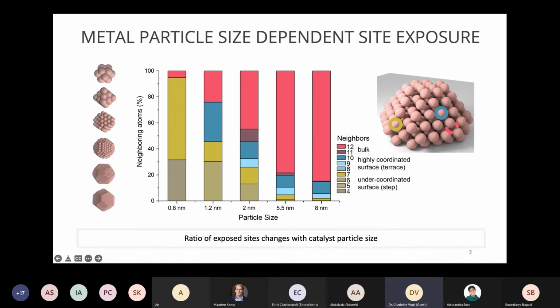And of course, in supported metal catalysts, we want to make as much use out of the often most expensive part of a catalyst that we have, which is the metal. So we want to make smaller and smaller nanoparticles, generally speaking. This allows more surface to be exposed relative to the bulk. And while doing that, while indeed creating more surface exposed for smaller nanoparticles, we also see a different ratio of sites for different catalyst particle sizes. So actually the types of surface sites that are exposed for different nanoparticle sizes changes. For a 5.5 nanometer particle, for example, you have a lot of this pink, which is bulk, basically, non-surface atoms.